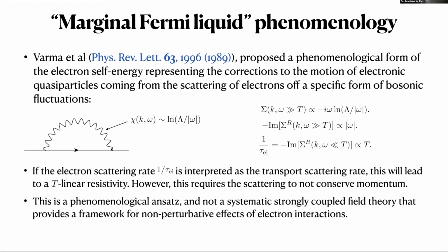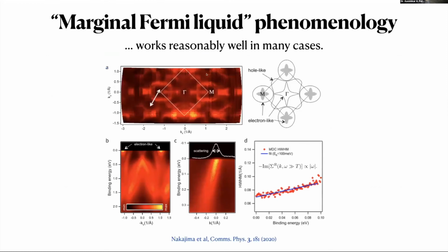And one has to come up with some way to derive this systematically in some field theory. However, it's a nice ansatz. There is actually experimental evidence for marginal Fermi liquid self-energy from ARPES, like in this pnictide material, where the self-energy is proportional to the frequency. It's a constant plus something proportional to the frequency.